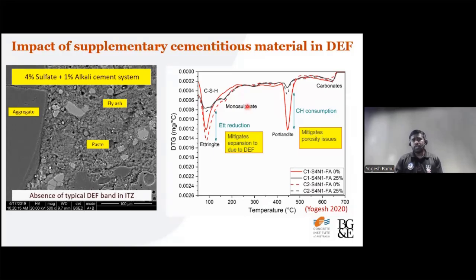So basically what fly ash or any other slag, any other SCMs do is consume a lot of calcium hydroxide and precipitate that into C-S-H. So there is a lot of pore refinement happening in the structure, which makes the concrete less permeable. Also, very little ettringite is precipitating in the system, so it mitigates the DEF expansion as well.